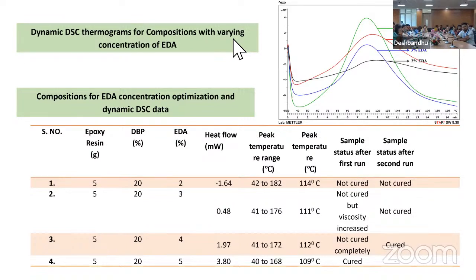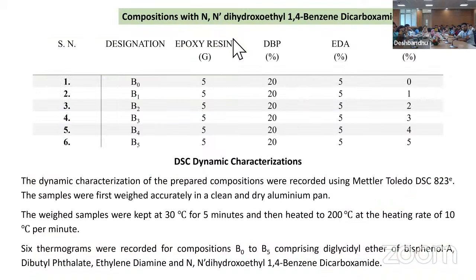So these DSC thermograms were obtained, and then we checked the DSC scan after curing, whether it is fully cured or not. At 5% of EDA, it was fully cured, and then we chose this formulation, and in this formulation, we added further our monomer, HEBD, from 1%, then 2%, 3%, 4%, and 5%. Then we carried out DSC dynamic characterizations for these formulations using Mettler Toledo DSC 823 with kinetic software.